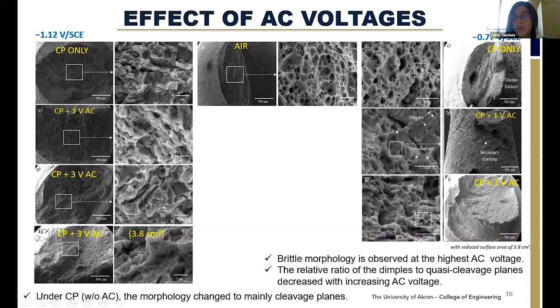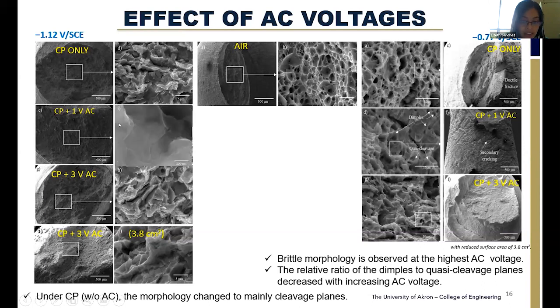However, when the sample is around -0.77, the fracture morphology changes from ductile to brittle when the AC voltage is increasing. We also found secondary cracking in the sample at -1.12, which is an indication of brittle fracture. And in the lowest cathodic potential, as you see here at higher magnification, 200 nanometers, we have microcracking.